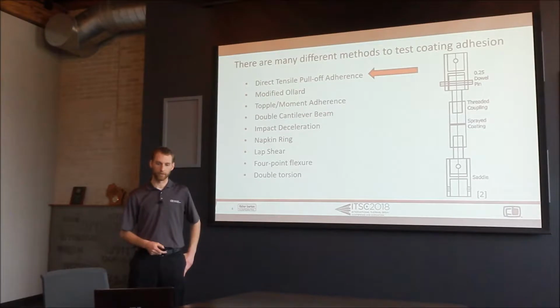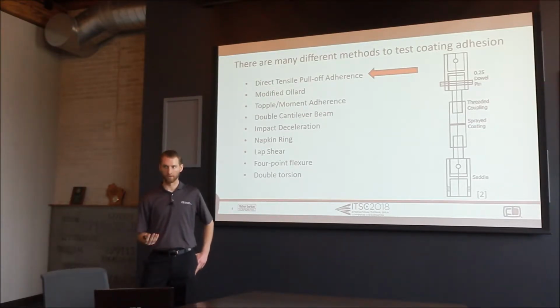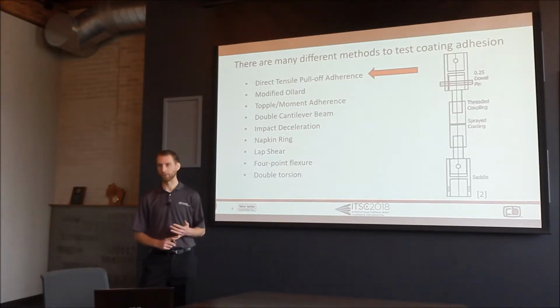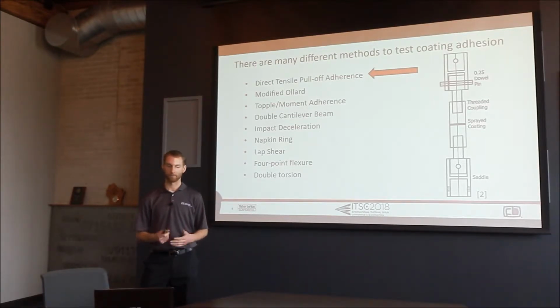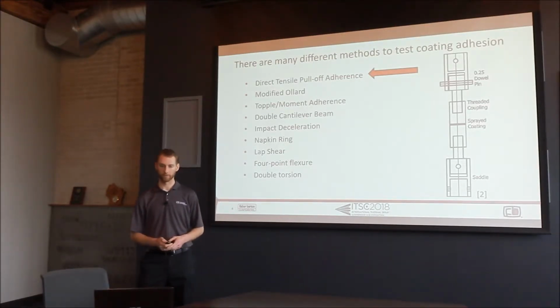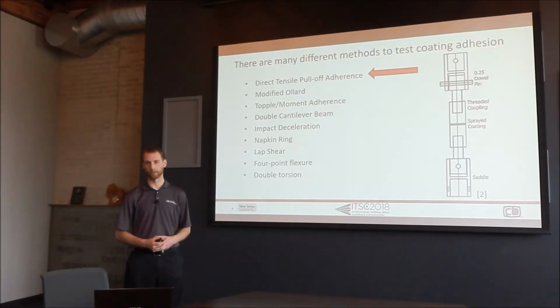We do know of quite a few pitfalls of this test method. Every aspect can create variance in the process and in the test, everything from the method that you use to cure the adhesive, to the geometry and how you're fixturing the parts as the adhesive is cured. But we are going to compare this test to our 4-point bend for comparison.